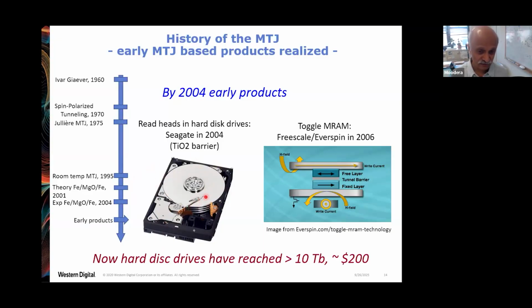So able to actually see extremely small signals very close, and they were able to utilize it in the read head of hard drives. That's 2004. Just imagine, within about 8-9 years, they were able to develop this. They used, of course, titanium oxide as an insulating barrier between the two magnetic electrodes.